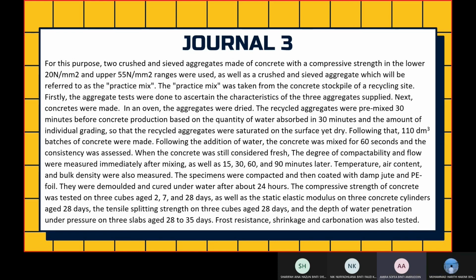Following the addition of water, the concrete mixed for 60 seconds and the consistency was assessed. When the concrete was still fresh, the degree of compactability and flow were measured immediately after mixing, as well as 15, 30, 60, and 90 minutes later. Temperature, air content, and bulk density were also measured. The specimens were compacted and then coated with damp PE foil. They were demolded and cured underwater for about 24 hours.